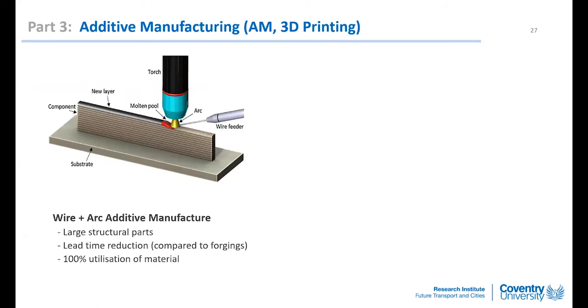So for my final 10 minutes, I still got 2 slides on additive manufacturing, then I will move on to composites. With additive manufacturing, most people are working on powder bed fusion. I had the opportunity to work with Cranfield University on wire additive manufacturing. That is an old welding technique, welding 1 millimeter diameter wire layer by layer to form an additively made part. The advantage of this over the powder bed is that they can make a large part, the build time is faster than powder, and there is also 100% utilization of material. So there's no wasted powder unused after the fusion.